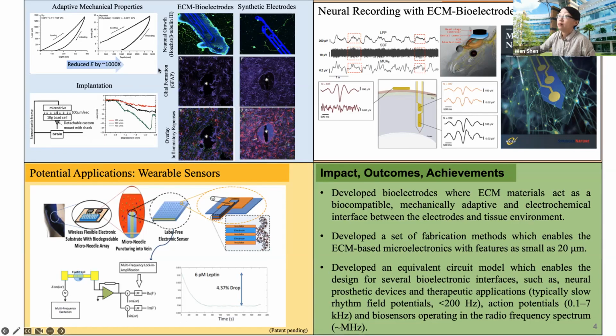And then in addition to the biocompatibility benefit, we also looked at the mechanical property of these bioelectrodes. So these materials are a type of hydrogel. So they are very stiff when they're dehydrated in the air. So that will facilitate the implantation of these electrodes. But after implantation, the fluid in the tissue will hydrate these hydrogels, and then they become very soft. So you can see the Young's modulus has decreased 1,000 times after hydration.